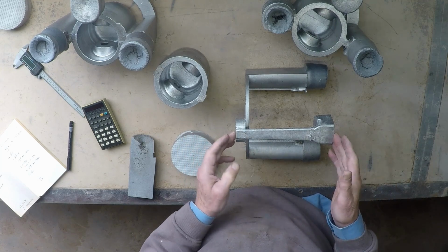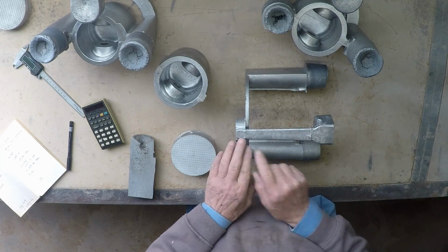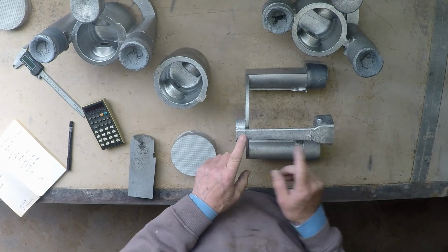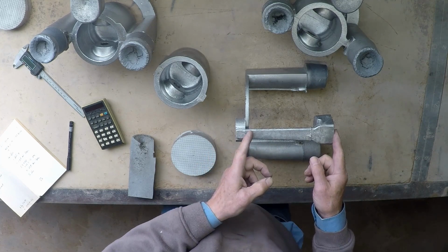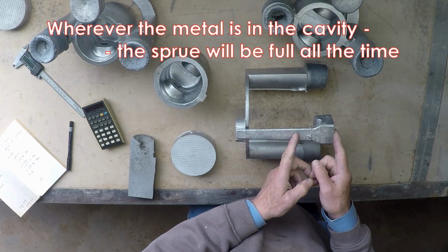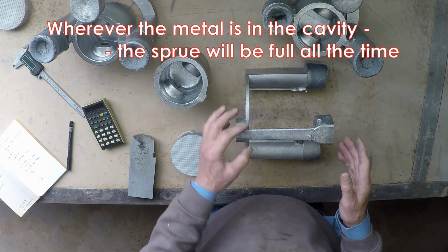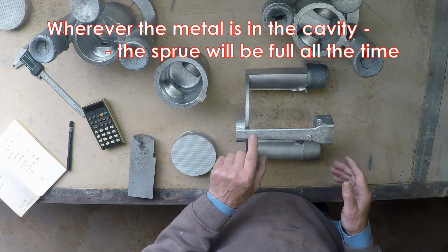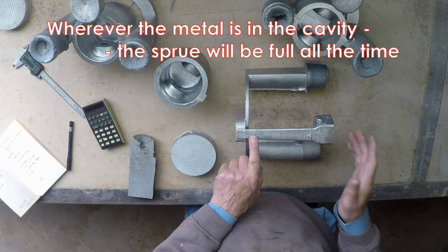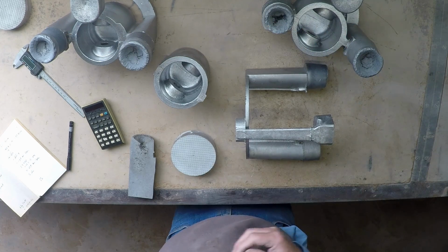Now, that's an initial flow rate when you first start to pour. As the casting fills up, of course, the head between here and wherever the metal is gets less and less, so the flow slows down, and that plus the friction that you get here tends to halve that value on average.